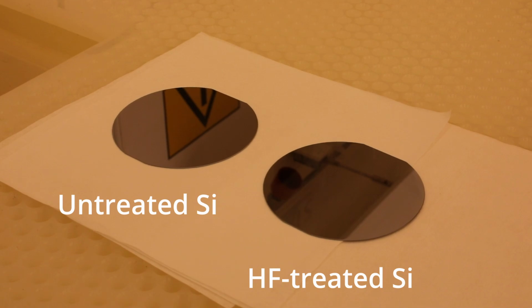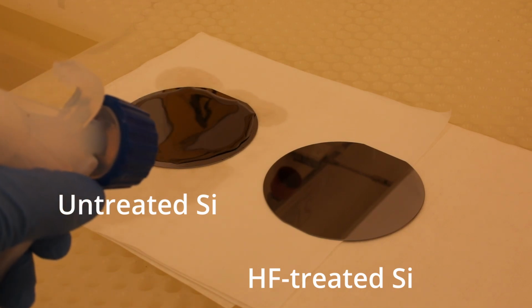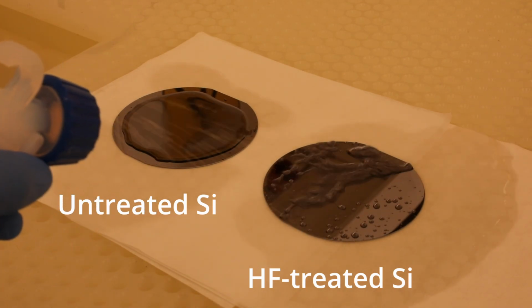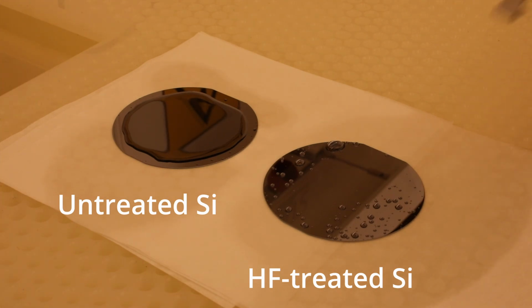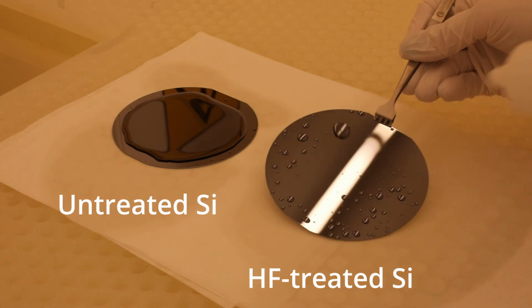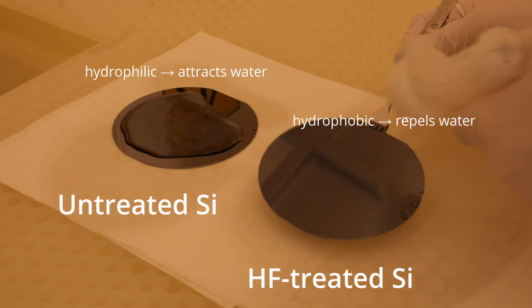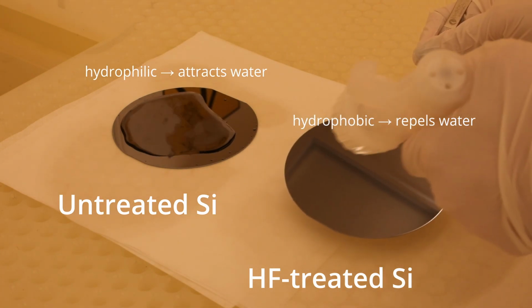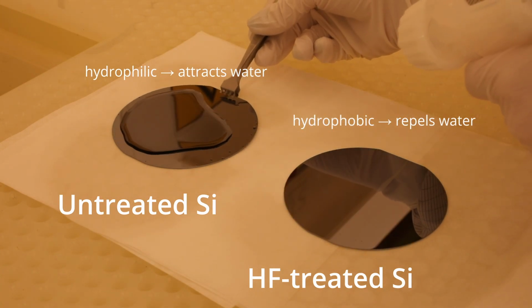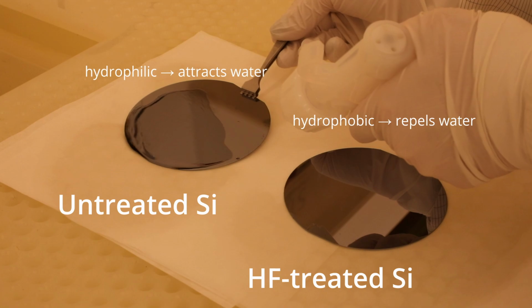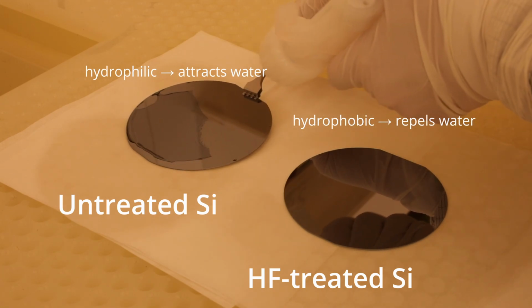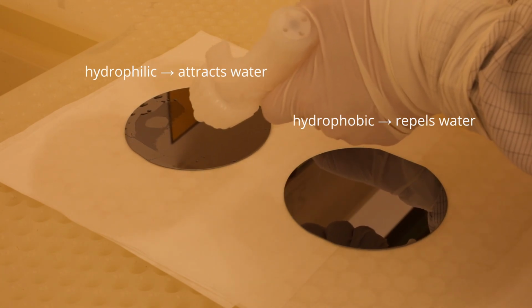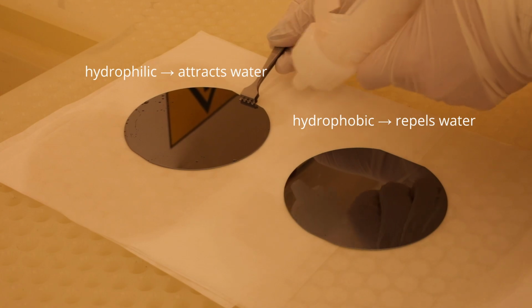Here we have a side-by-side comparison of two silicon wafers, one that I did not treat with HF and one that did receive the HF treatment. You can see how the HF-treated wafer repels the water I spray on. The water forms small droplets to minimize its contact area with the now hydrophobic surface of the wafer, and the droplets fly off as soon as I spray them with a stream of nitrogen gas. On the other hand, the native oxide of the untreated wafer is hydrophilic, and the water forms a giant blob that is quite a challenge to spray off.